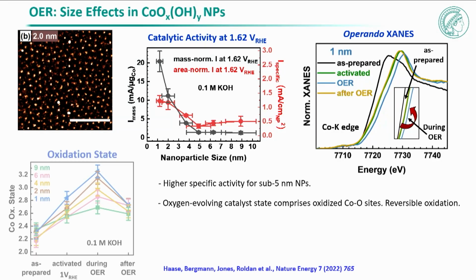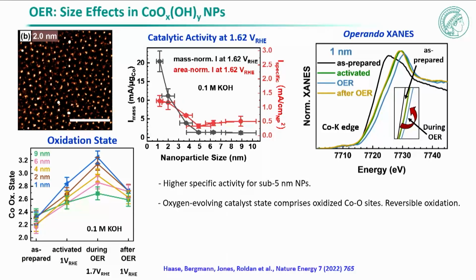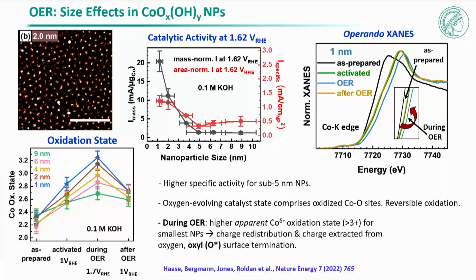And there is also a size effect. If you look at particles with different sizes and you look under reaction conditions, for example, the oxidation state of cobalt appears to be slightly different. We know now that it's not so simple, that there is a charge redistribution between the cobalt and the oxygen, and that we have the formation of these oxyl species. This happens for these cobalt oxides. This happens also for iridium oxide. But this type of information is key in order to understand what material do I need to make my electrolyzer more efficient and also more stable, and minimize the amount of metal that I'm using, especially for the people that were working with materials like the iridium oxide.